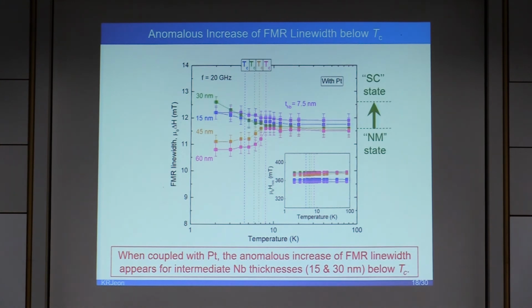Let me now focus on the key result of this work. In other words, the suppression of dynamically driven spin current flow at low temperature by singlet pair correlation can be greatly modified when an effective spin sink such as platinum is coupled with the superconducting niobium layers. This figure summarizes the obtained FMR line width as a function of temperature from platinum SFS platinum structures with different niobium thicknesses at the fixed microwave frequency of 20 gigahertz. The most important aspect of this data is the remarkable enhancement of FMR damping for the intermediate niobium thicknesses of 15 and 30 nanometer below Tc when coupled with platinum layers.